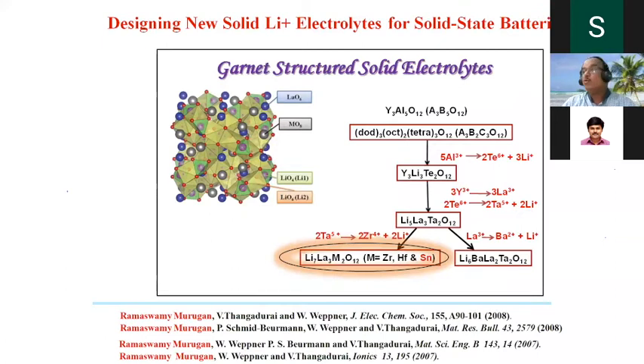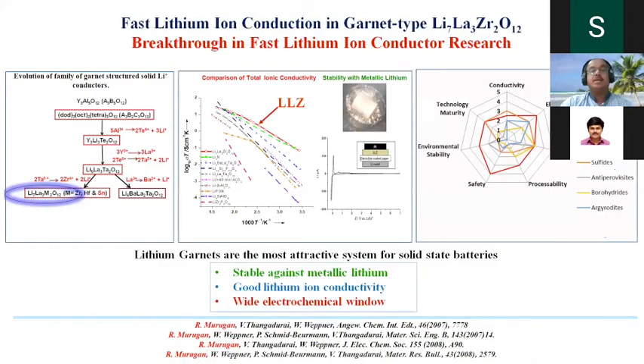This is how we entered into what I call zirconium containing lithium garnets. It started from here. Then moving from Li5 to Li6, Li6 to Li7, then zirconium, hafnium, and others, but zirconium is the best composition. So this is how we ended up with what we call zirconium containing lithium garnets. It's the biggest breakthrough in fast lithium ion conductors.